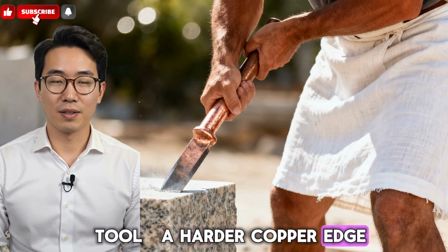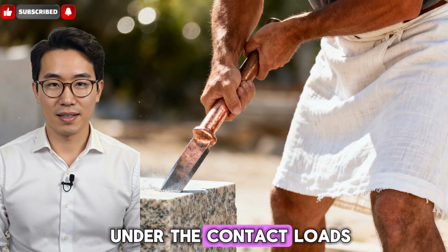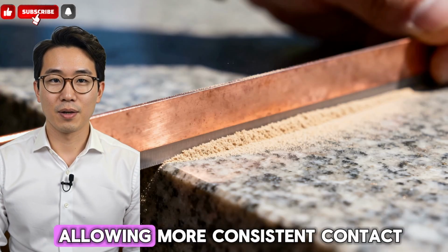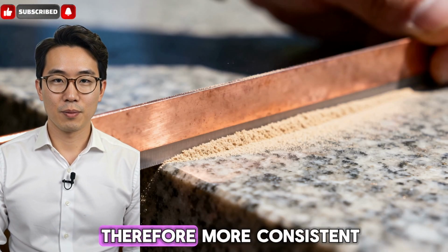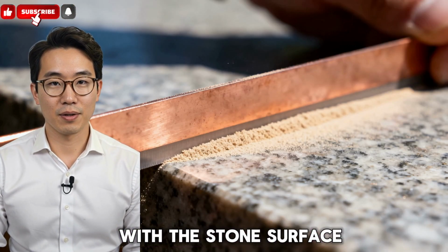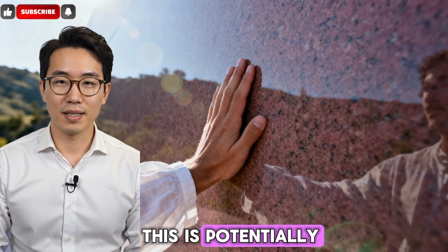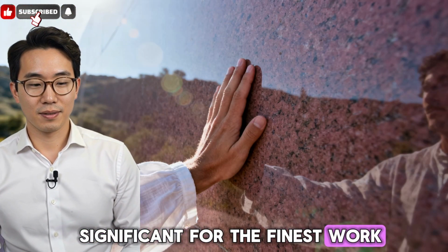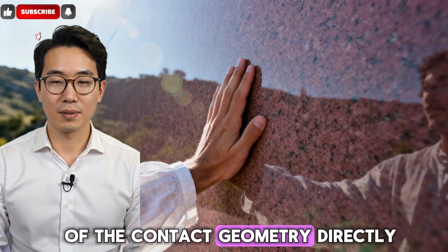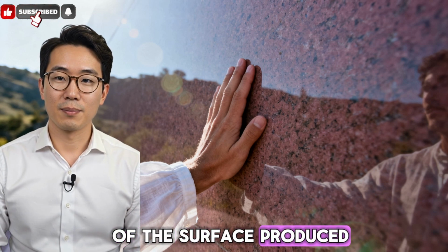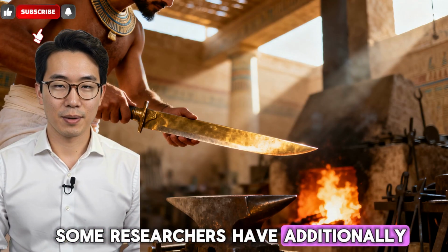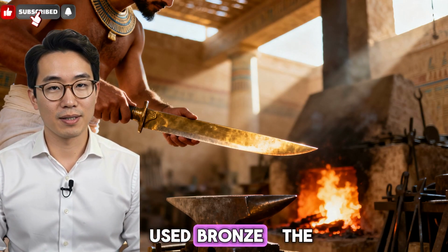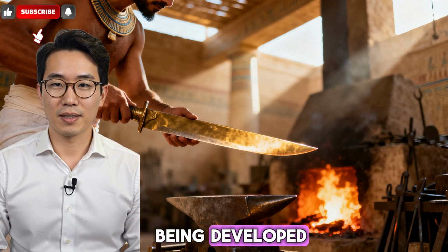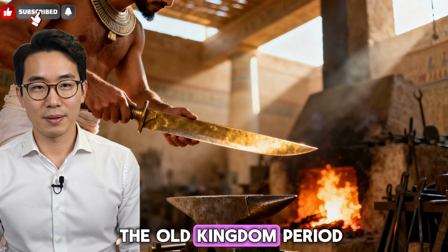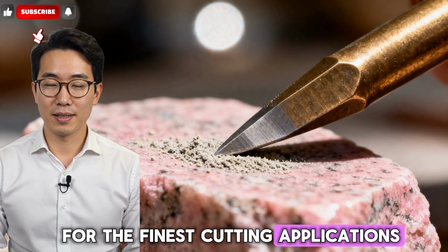A harder copper edge would maintain its shape longer under the contact loads of the grinding process, allowing more consistent contact geometry and therefore more consistent abrasive contact with the stone surface. This is potentially significant for the finest work, where the consistency of the contact geometry directly affects the uniformity of the surface produced. Some researchers have additionally proposed that the Egyptians may have used bronze, the copper-tin alloy that was being developed in the ancient Near East during the Old Kingdom period, for the finest cutting applications.